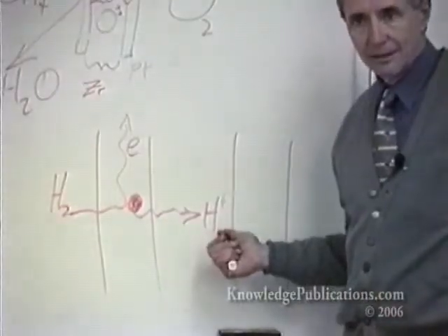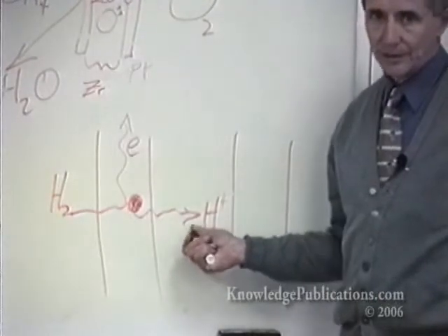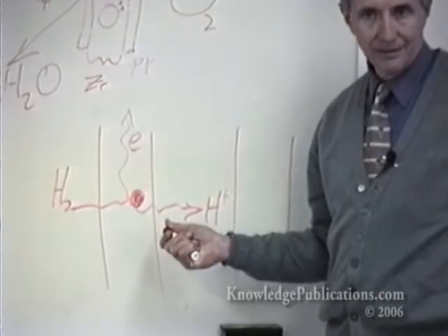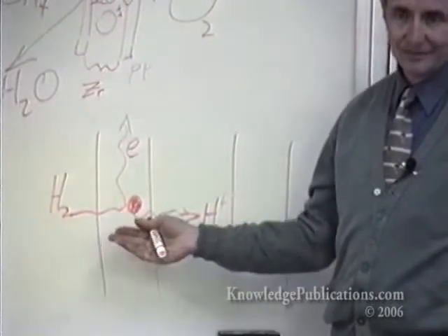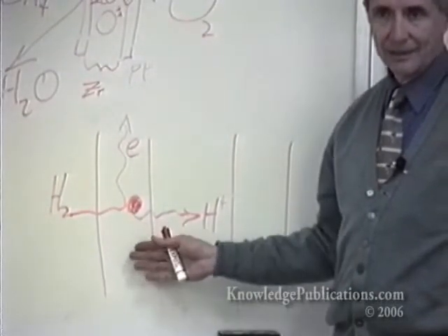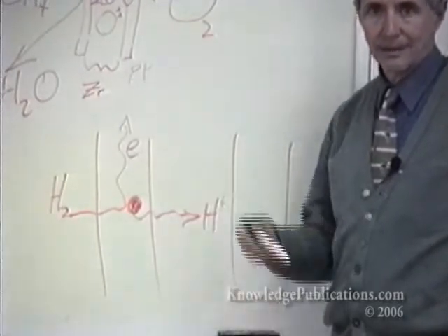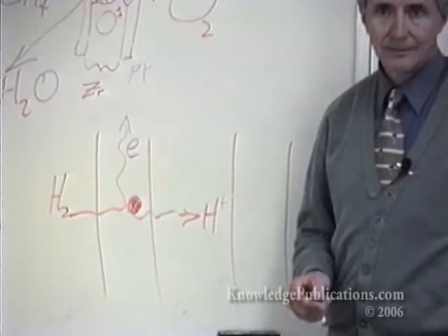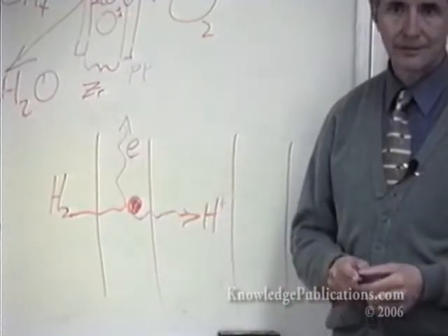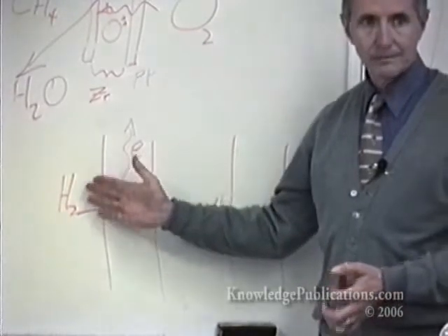It lowers the efficiency. It may produce so much heat that it ruins the fuel cell. I produced cells that I thought were going to be gee whiz good ones, and made the mistake in testing them and getting the pressure too high, forced the diffusion to the point that they changed the membrane. They lost conductivity. Which brings you to the development of adding pressure.